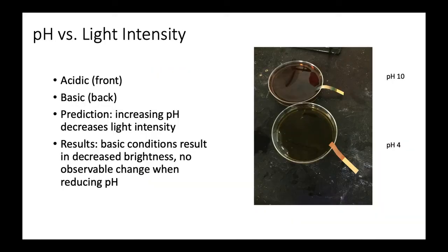It has been reported in the literature that oxidation gradually causes quantum dot brightness to decrease over time, but quantum dots are also highly sensitive to pH. The pH of the environment modulates the surface charge of the semiconductor nanocrystal, its stability, and its solubility. And so I was anticipating that increasing the pH by pouring NaOH into one of the petri dishes would cause the light intensity to decrease, and that if I poured in more acid, the light intensity would increase.